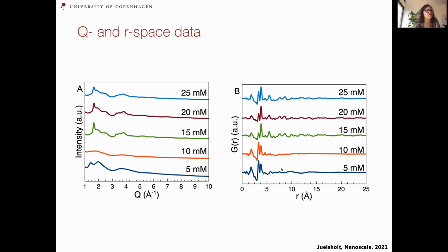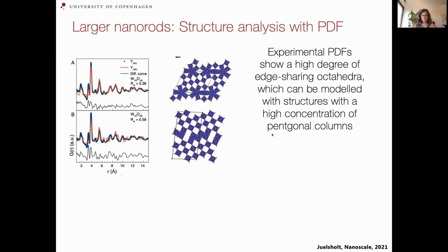And then, well, we could get these PDFs as we have here, and now we can start analyzing them and understanding the structures of the nanorods. So we start with these nanorods here. Usually in the literature, what's assumed is that these nanorods take the tungsten oxide W18O49 structure. And here we've taken the experimental PDF in blue, and then the calculated PDF in red from this structure, and then a difference curve. And we see that it fits fairly well.